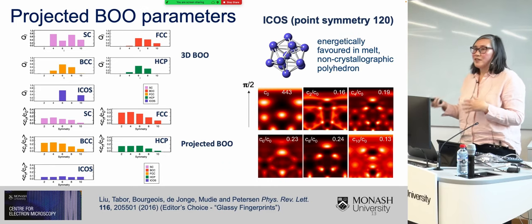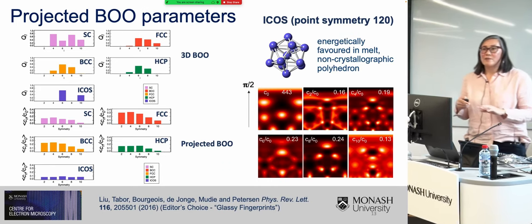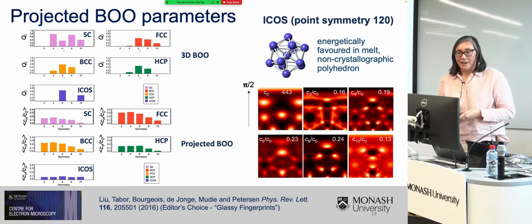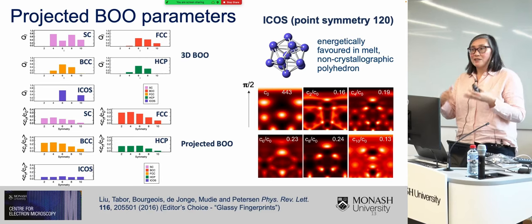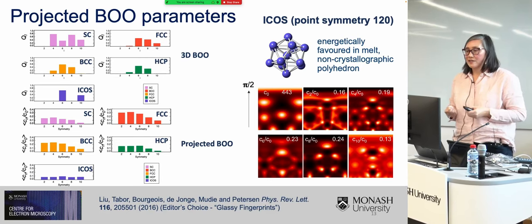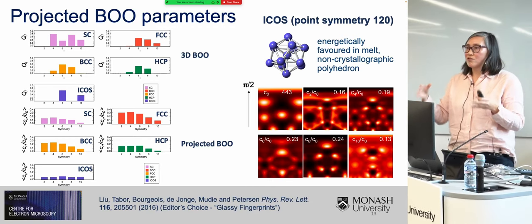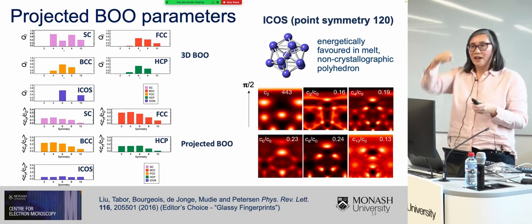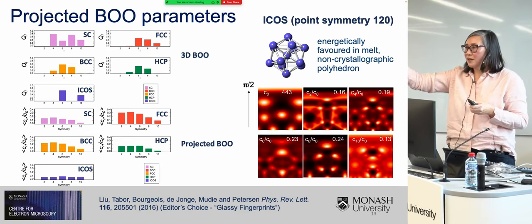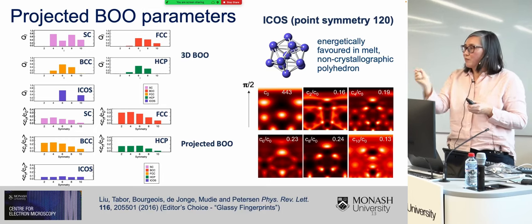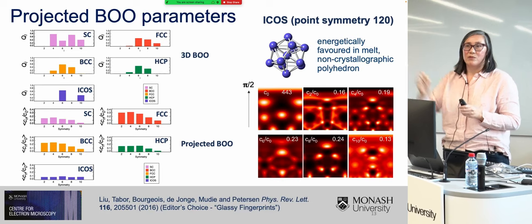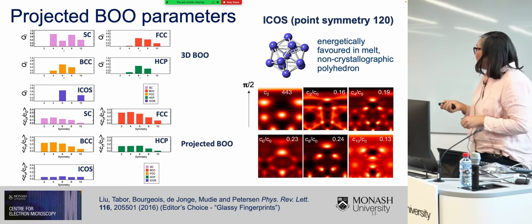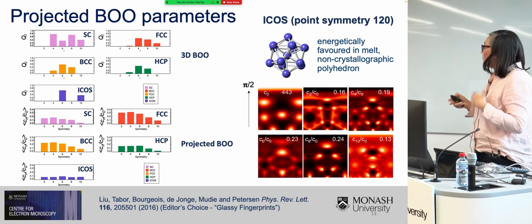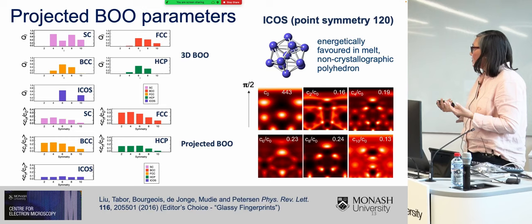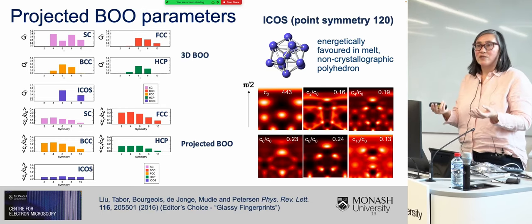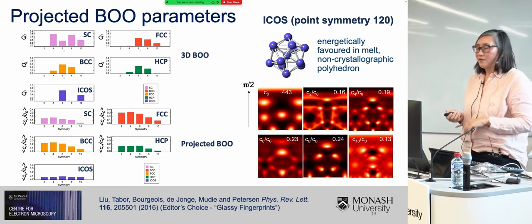Now, glasses are very inconvenient because they lack translational symmetry, but sometimes they can help you out in a certain sense. The glass is isotropic and all directions are virtually the same. So if you do have a prominent structural motif in your glass and you scan your beam across the material, then you will also be sampling this prominent motif in every single possible orientation. Using this fact, I tried to calculate some projected bond orientational order parameters to see if they would give me a strong fingerprint of the different kinds of order that I might have in my glass.